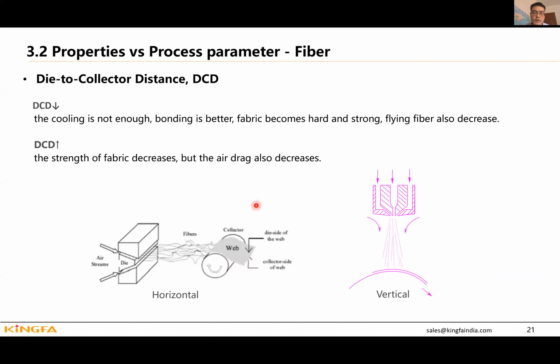During our production, the collector is far from this die, but after normal production, we need to move this collector close to the fiber, to this die. If we decrease the distance, that means the cooling is not enough, and the fabric bonding to each other is much better. Then the fabric can become hard and strong, and also the flying fiber will decrease. So we should find a suitable DCD distance.